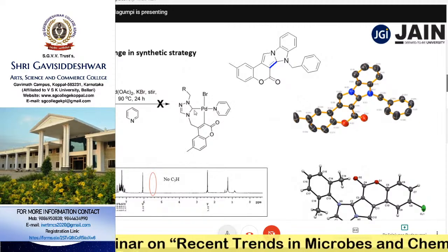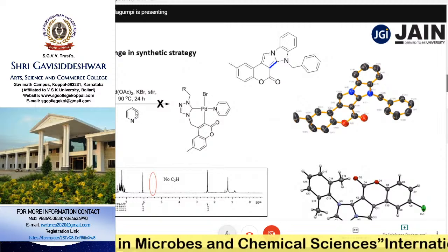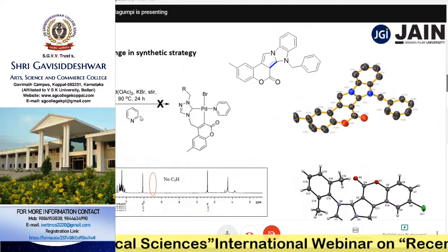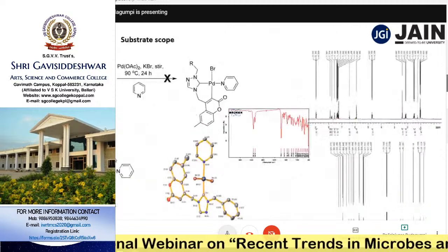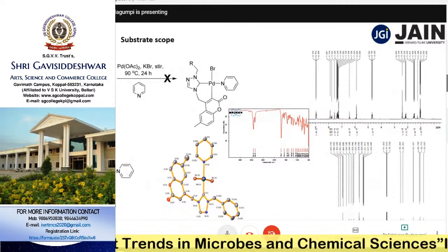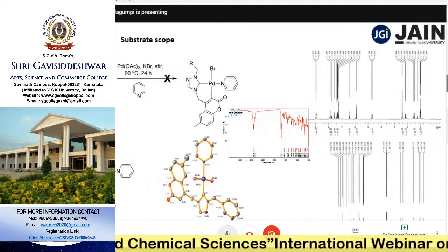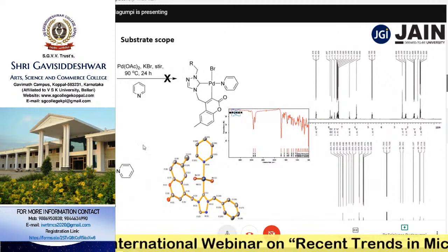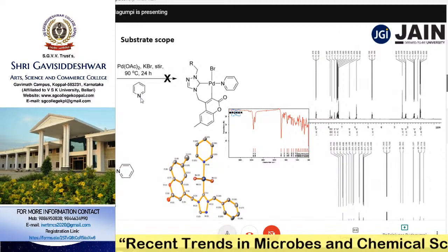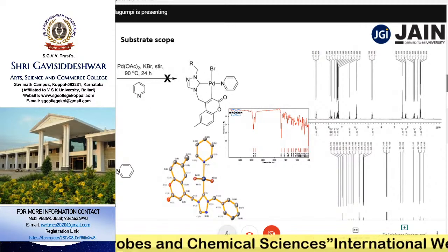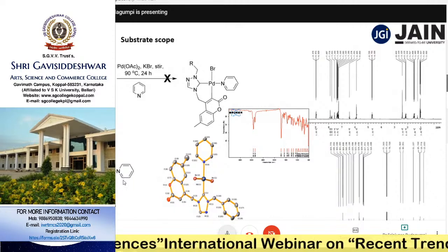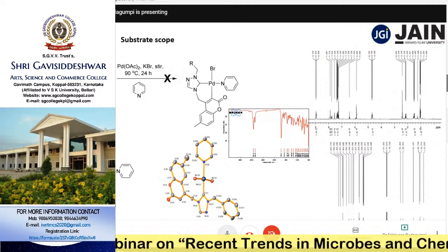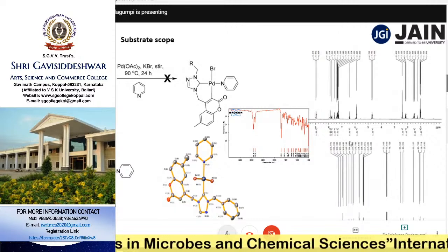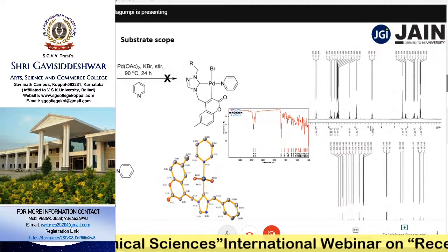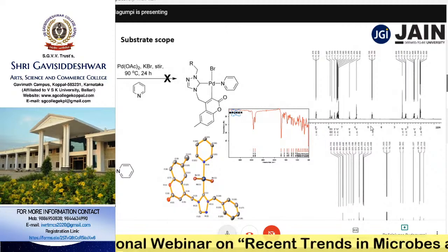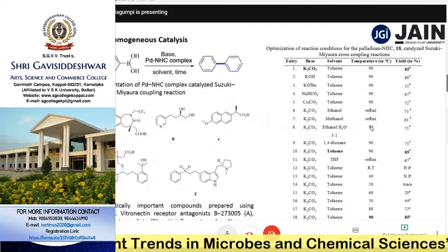Our efforts did not give this one by changing the palladium, by changing the solvent, that is strong base pyridine. While in the other case, we were able to get again this kind of complex formation. That is a triazole on one side, bromidos are there, but on the other side of the complex we have pyridine, since we have used pyridine as a solvent. So we did not get the earlier kind of complex formation, while we got this particular type of complex formation, right? And this is called pyridine enhanced precatalyst preparation, stabilization, and initiation. Now these were further characterized by IR and NMR spectroscopic techniques. Now we have used all these complexes as homogeneous catalysts.